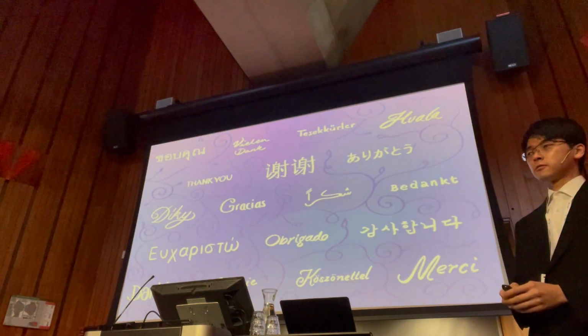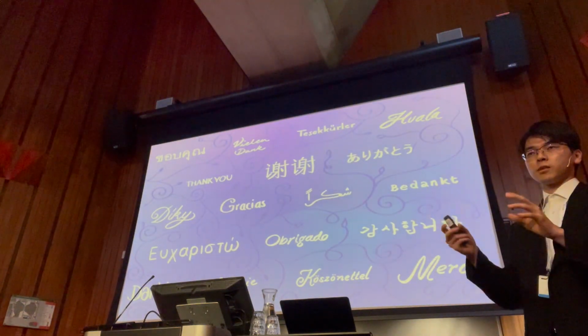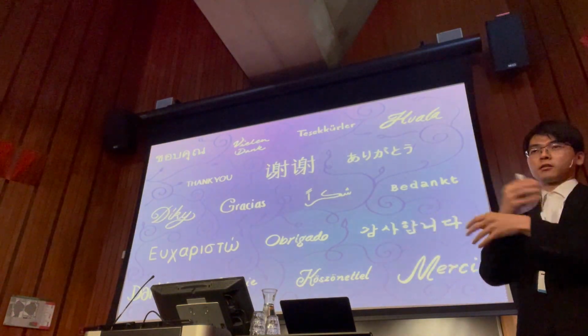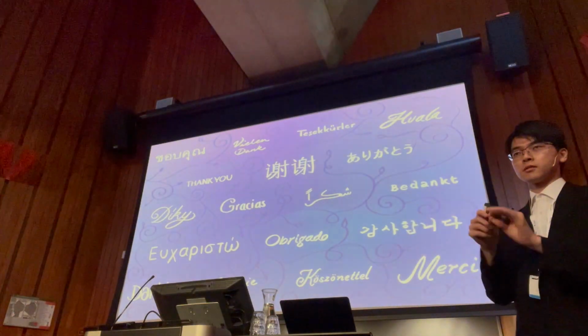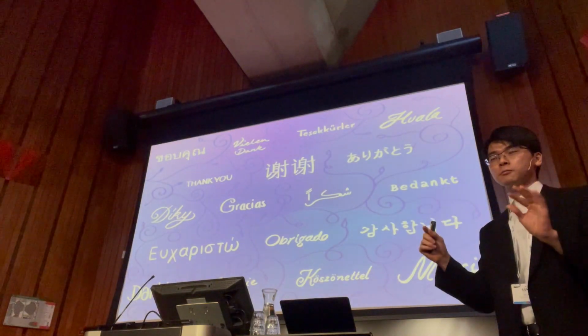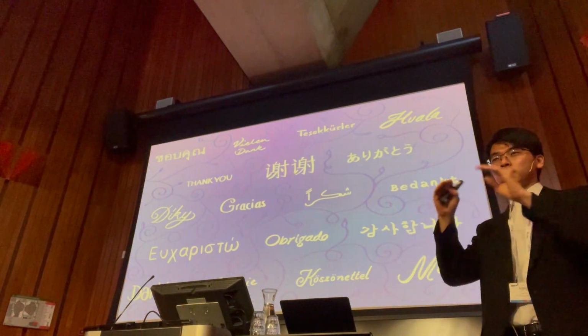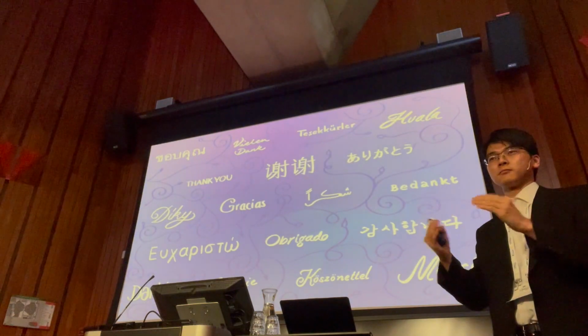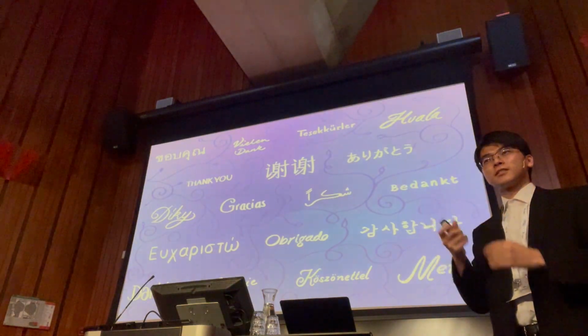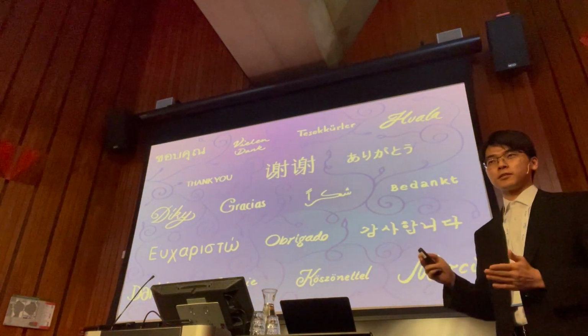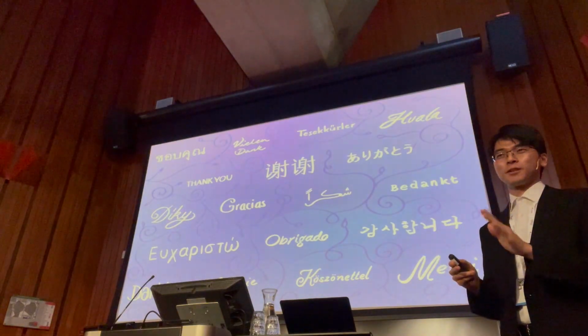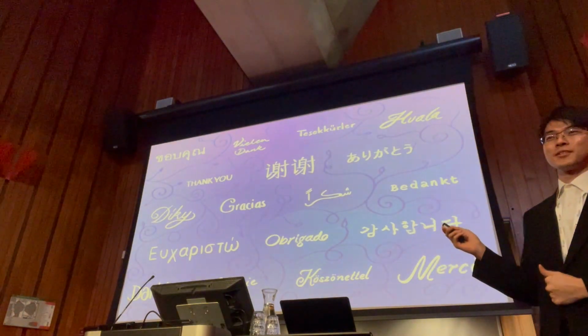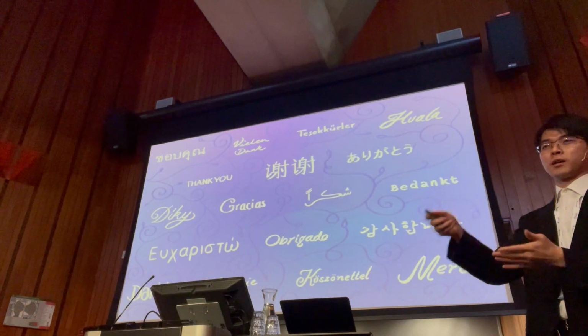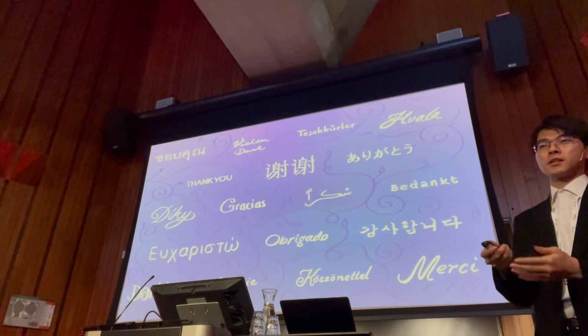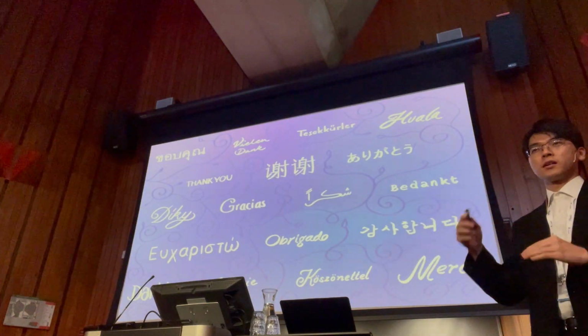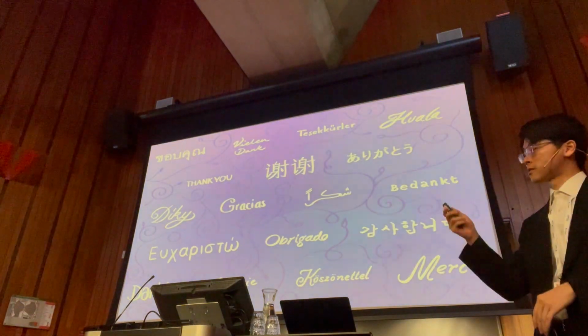Yes. So we mixed the polymer and MXene together. It's just powder and polymer mixed together. So it's actually just a single layer, which is interesting because it still made a bilayer-like bending for some reason. So your actuator is composed of only one layer. Only one layer, which is weird, but that's what we saw on video in some cases. Of course, we also tried with bilayers in the recent few weeks, and they have much more reliable performance. It doesn't vary as much as this one.